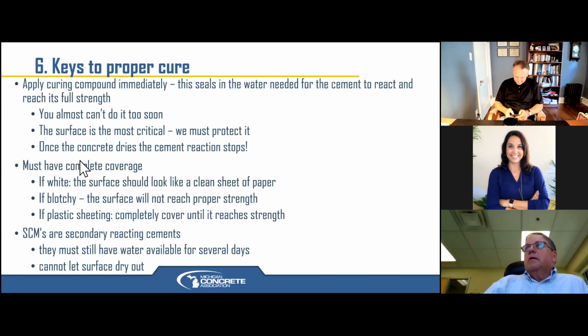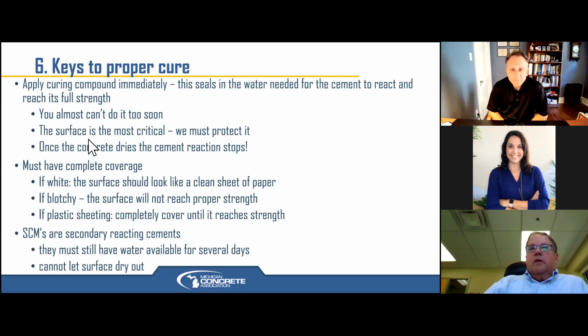Curing. We want to talk about curing a little bit. We need to apply this curing compound immediately. This seals the water in. You almost can't seal it too soon. Also note that the bleed water is being reduced. So we need to keep that water there so we can fully hydrate our mixes.